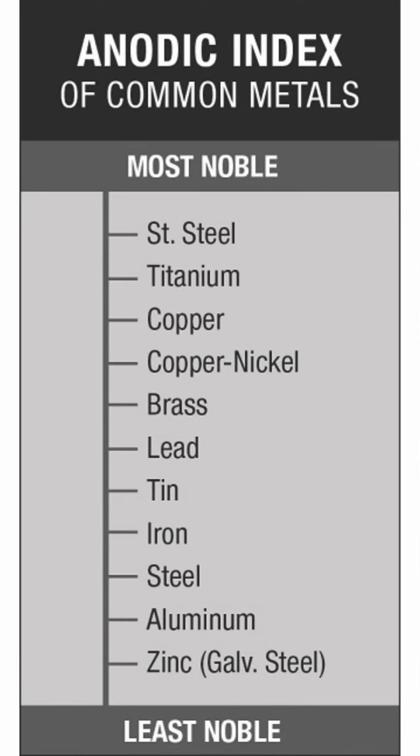So in that instance, that brings us to option number 2, which is the brass nipple, which kind of creates a smoother transition. So if you had galvanized pipe and you're going to copper pipe, you throw that brass nipple in there to kind of ease that transition, because if you look at the anodic index, brass is in between your galvanized and copper pipe. So it just makes it a little easier of a transition to help prevent that corrosion from happening quicker.